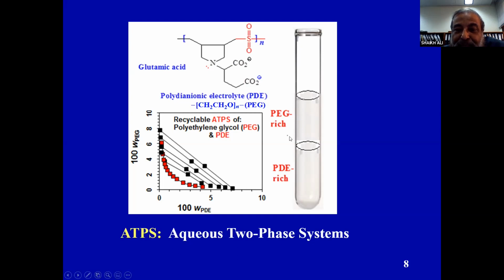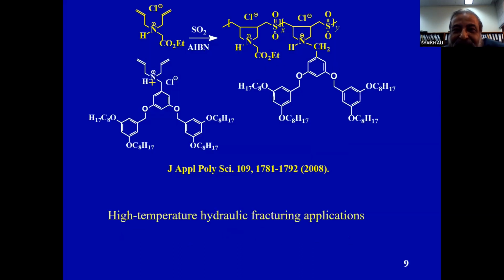a mixture of proteins, it is expected that one of them will go to one of these layers, one of this anionic, it has amino acid residues of glutamic acid, and here you have polyethylene glycol. So the protein will selectively go into one layer that will help us separate the biomolecules. Now you have another one here with dendrimeric pendants. And these dendrimeric pendants can increase viscosity tremendously. And that could be used in high temperature hydraulic fracturing applications.